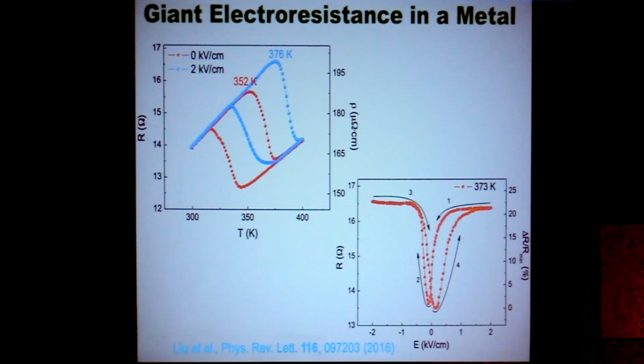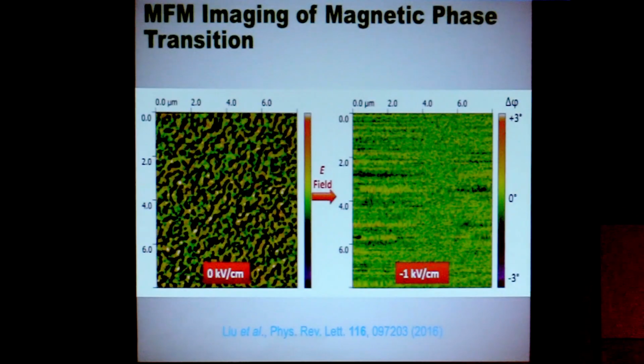It's a very metallic alloy, so this 20% resistance change at around 100 degrees Celsius is quite large. This is, of course, because of the magnetic phase transition. This is actually quite similar to the so-called phase change memory, and to me it's also like the CMR system, and also the new concept proposed by Thomas today, the so-called texture magnetic systems. All are similar to this kind of thing.